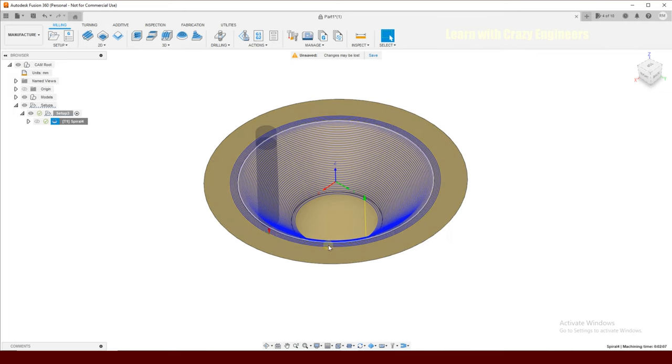But from my experience, this kind of movement is better because the tool takes a little bit of time from the outside movement, then slowly moves into the forming region. Sometimes making a 0.25 millimeter movement suddenly into the center, that sudden deformation can cause some fracture in the sheet if your sheet thickness is very small, like 0.5 or 0.3 or even sometimes 1 millimeter, because as I said before, the deformation is based on local material deformation. So when the forming tool suddenly causes 0.25 millimeter at one place, it causes a punch movement. It's like you are suddenly punching the sheet from the top. So there is some chance that it will make a fracture on the sheet. So be careful about that one.